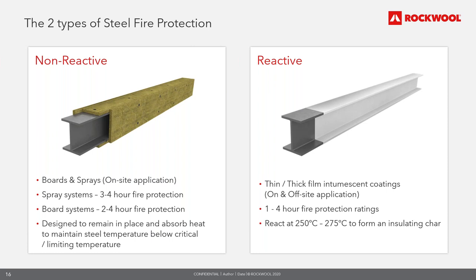At these temperatures, the properties of the steel will not be affected. And as a result of this reaction, they swell and provide an expanded layer of low conductivity char. Intumescent coatings can be divided into two broad families, either thin film or thick film coatings. Thin film materials are mainly used for buildings, whereas thick film intumescent coatings were originally developed for the offshore and hydrocarbon industries, but they have been modified for use in today's buildings.